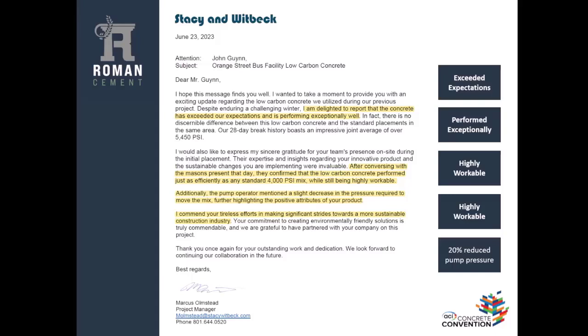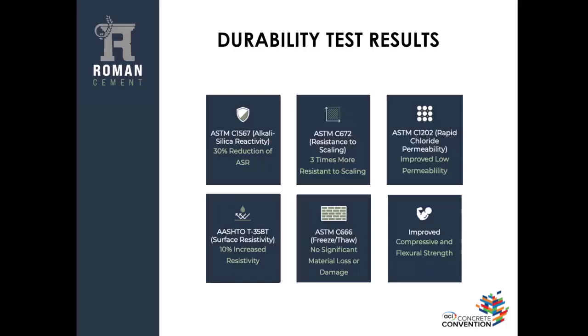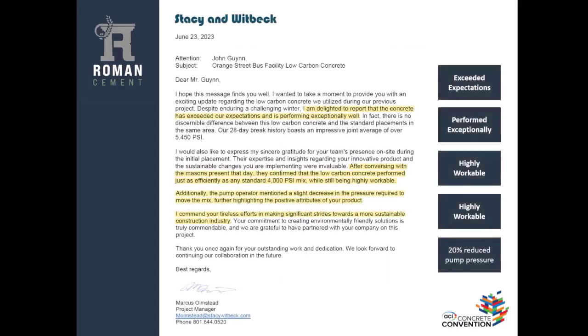This is kind of a summary, but the company who pumped it said that the pressure required to pump the concrete went down by about 20%. There is a statement here that the average strength from a 4,000 PSI air entrained mix was 5,450, and one of the trucks was actually 6,200. This is an average. They actually added a little bit more water at the end after doing the air test, and they got lower results. So this is just the average, but it was a poor average. But they said that it performed well and finished well. Anyway, they thought it was a very good project for them, and they enjoyed working with it.